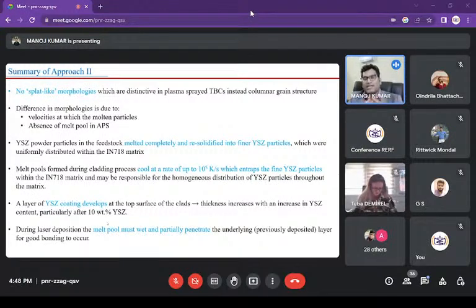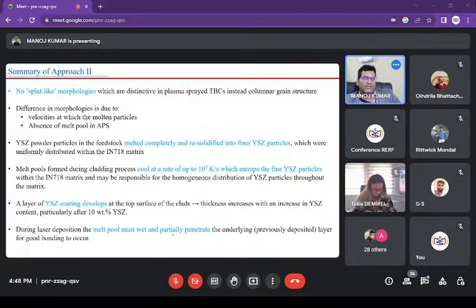if the YSZ layer is continuous throughout the coating, then it can also serve as a separate 100% ceramic coating, and that can further help in reduction of thermal conductivity. That can be a welcome offer, but it is not very welcome when we look for having multiple layers. So we have to understand. If you can develop a sufficiently thick layer in one layer of deposition, then this is advantageous. But if you look for multiple layer deposition, then this is disadvantageous. So we have to deal with it accordingly.